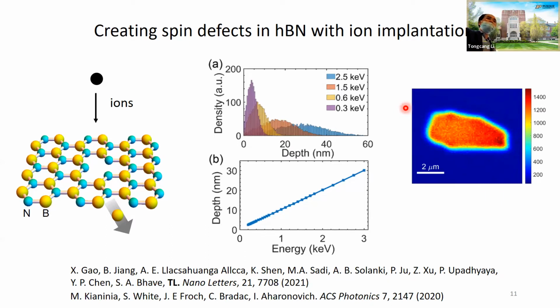You mean this one? In this case, we irradiate homogeneously, so there's no resolution. The whole flake will have spin defects homogeneously. But that will be on a millimeter or centimeter scale. Our flake is not that big. Our flakes are typically on the order of 10 micrometers to 100 micrometers maximum. Within that range, we can choose it as homogeneous.